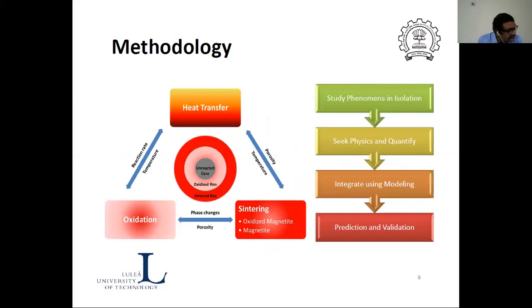But on the magnetite pellet, the magnetite gets oxidized, and then it also gets sintered. Of course, the sintering can happen both for magnetite as well as the oxidized magnetite, which is the hematite. And interestingly, the sintering characteristics of the oxidized magnetite are different from the magnetite itself. Rather, what happens if you take a pellet, it starts oxidizing from the outside, and then you have an unreacted core which is magnetite. As temperature increases, this will sinter separately, and that will sinter separately, and their sintering characteristics are different. Rather, magnetite sinters a bit more easily compared to hematite.